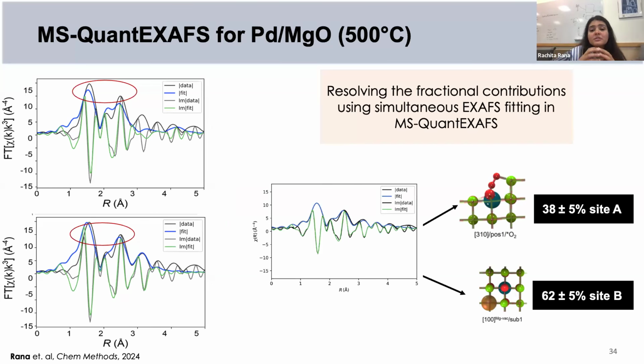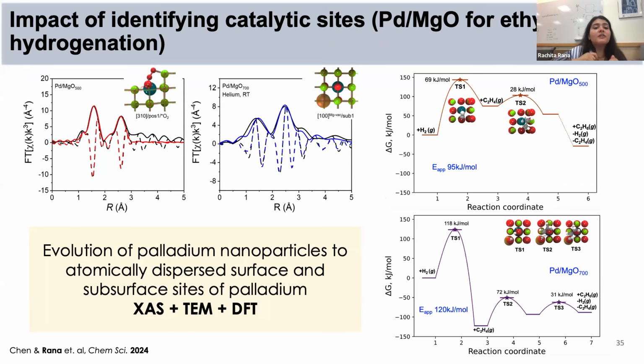calculations, where we found that because the 700 site was much more homogeneous, the apparent activation energy of the reaction matched beautifully with the calculated barriers from DFT, whereas because there was heterogeneity in our 500 site, the barrier that was calculated was much lower using DFT as compared to the actual apparent activation barrier for the ethylene hydrogenation reaction for this catalyst, because we were accounting for just the surface site, which was much more active as compared to the subsurface site.